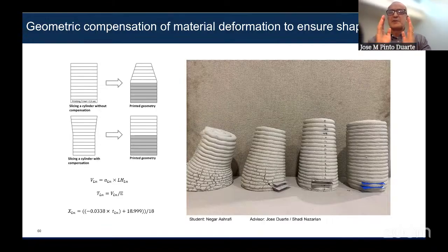The problem was the pillar was too small, so when it was printed, it allowed lots of deformation. And because of that deformation, we were not able to insert the window frames automatically. So this triggered work to understand how the material deforms. If you need to print a cylinder in a small part and you don't do any kind of compensation for the deformation, what's going to happen? You end up with a truncated cone. The bottom layers will deform under the weight of the subsequent layers. So you need to change that.